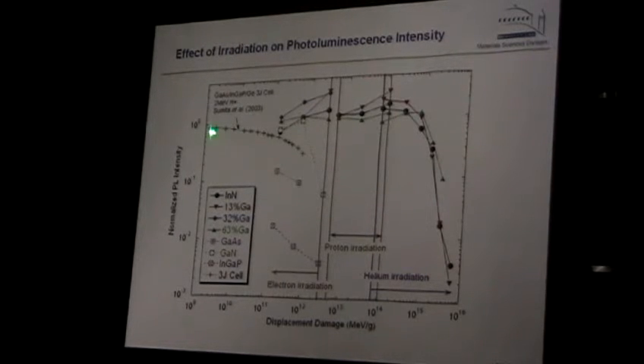And this is how the solar cell behaves in space. The efficiency of the solar cell goes down also with the damage. And the figure of merit is that if efficiency goes down by 20%, it becomes unusable. So it has to stay within 80% of its original efficiency. And then, of course, the question is, how long does a satellite live, and how much damage can it take before you have to replace it?